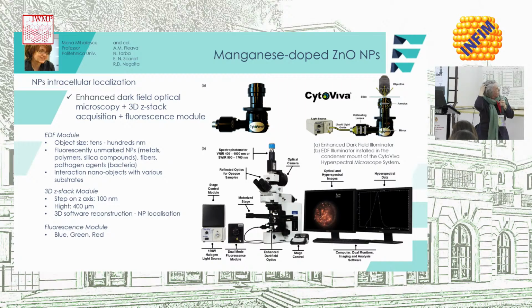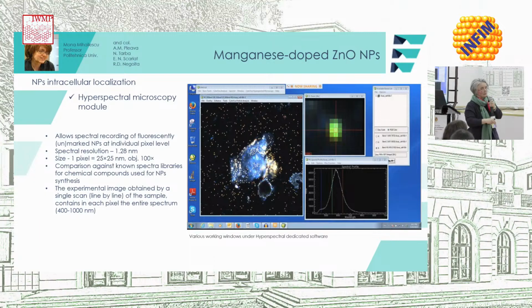Further, we tried to find a way to see where these nanoparticles are going. And for this, we used a system for 1,000 nanometer in each pixel. You can see here an image of the working software window, and you can see here a zoom on a pixel. And here this is a field with a lot of nanoparticles dried on a glass.